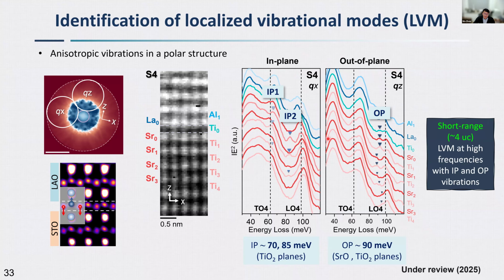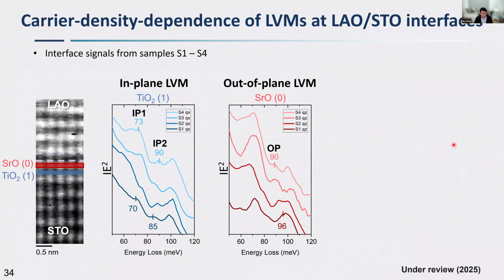And the interesting thing is the out-of-plane vibrational modes, you can see that in both the strontium oxide layer and the titanium oxide layer, but the in-plane modes, you only see that in the titanium oxide layer. So it's highly localized. And I should mention that this very short distance is consistent with what people found for the superconducting layer thickness in this system. So we believe these localized phonon modes are actually correlated with the superconductivity.